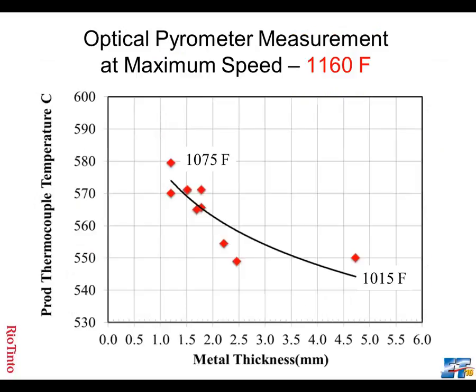This is some data we recorded a long time ago, back in British Alcan Extrusions days. What we did here was run a series of dies at maximum speed. We determined maximum speed as the beginning of speed cracks, surface melting, a bright surface, which is about 1160 Fahrenheit, 630 Celsius. And we found that the optical pyrometer measurement at this point was substantially lower than the bearing temperature. Yes, we know that.